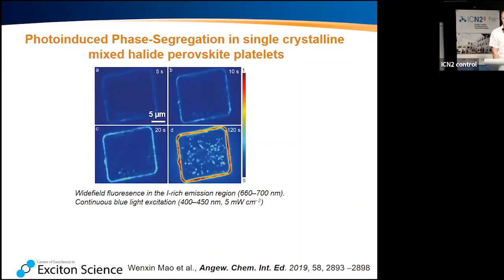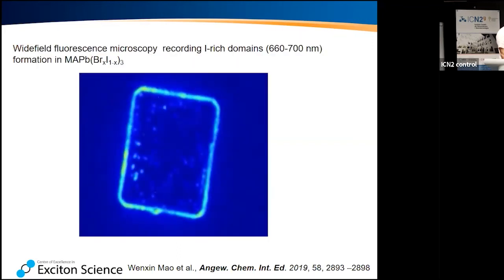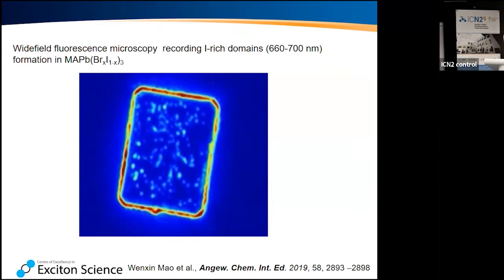So what we do now is we take one of these platelets and we shine light on it. And we have a fluorescence microscope camera that is only sensitive to the iodide-rich fluorescence. So if we don't form the iodide-rich phases, we're not going to see anything. You see here at the very beginning, this is what we start off with. So let's see whether that video is playing. Oh, okay. Lucky day. So this is in real time.